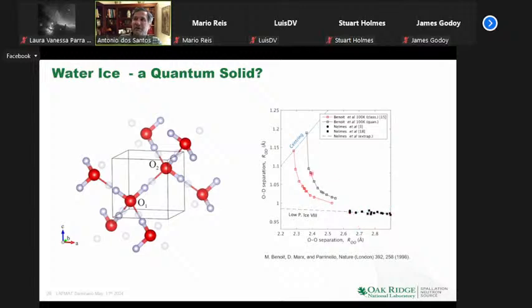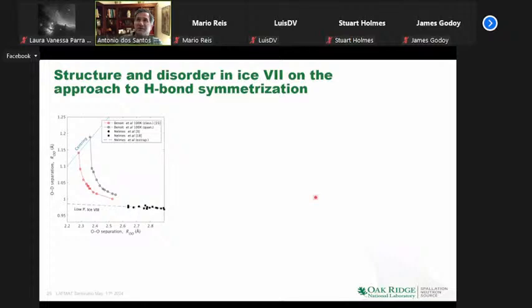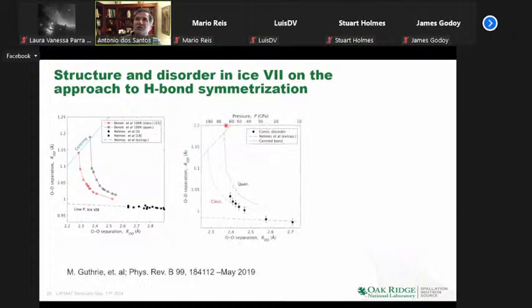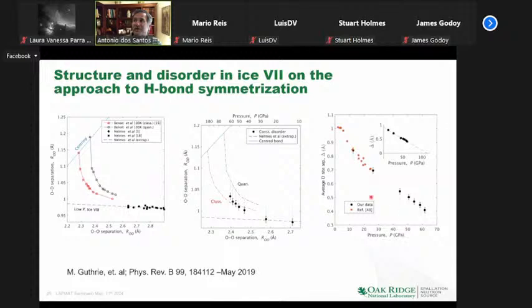So we're very far, at the low pressure ice, from this regime where you can start seeing these contrasts. This is the same I was showing you. And by extending it to 60 GPa with these neutron measurements, you could see you start classical. It does seem that as you approach the centering, you do have to account more for the quantum aspect of the hydrogen, which is not surprising. Now, as I said, we did refinements up to just shy of over 60. If you extrapolate, you get to ice X, the ice where the centering happens, at about over 100 GPa. Unfortunately, that has not been achieved yet, but we're still trying.